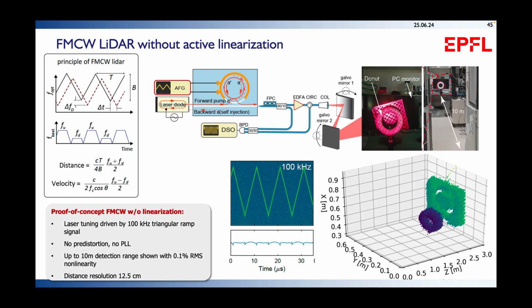But it has one challenge. You need very linear lasers for this, with highly linear chirps to generate the beat note. And this can be done using this aluminum nitride due to the high linearity of the actuator. And this shows a very simple point cloud here of a ring and donut that we've mapped in the lab using this aluminum nitride endowed low-loss integrated photonic circuits.